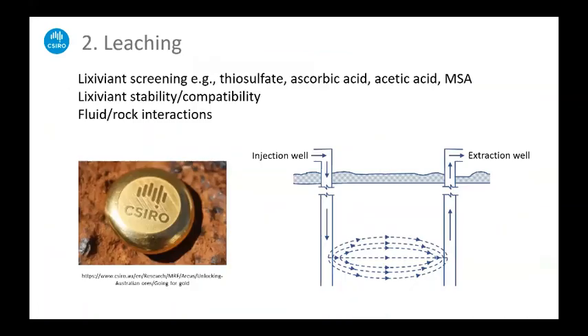That's containment. Onto leaching. That's very much the area that I work in and that my group works in. And we focused very much on lixiviant screening, because there's the potential to use more expensive and exotic reagents than might be used conventionally. We've looked at reagents that probably wouldn't be considered for conventional processing. We've looked at thiosulfate, for example. Thiosulfate is a potential alternative to cyanide. So cyanide would probably never be used in an in-situ environment for gold extraction.